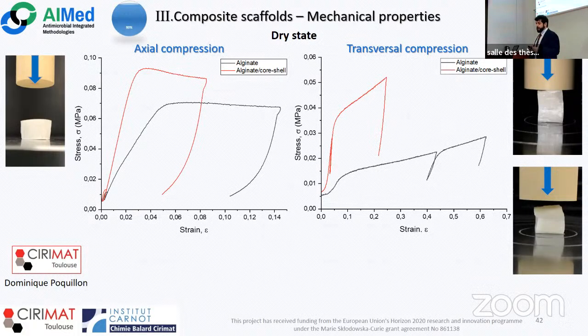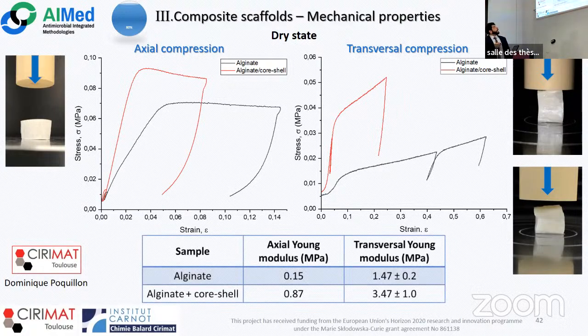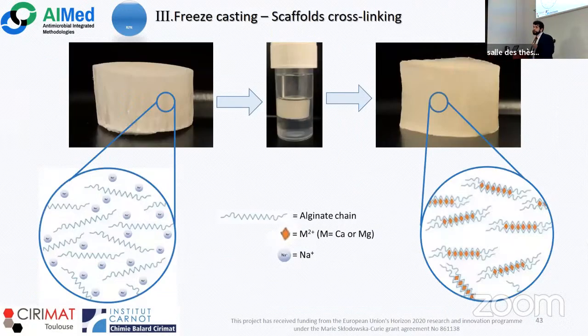Here at CIRIMAT, we also made some preliminary mechanical tests on the dry scaffold that we just prepared. And we can observe, comparing with the alginate scaffolds in black, both in the transversal compression and in the axial compression of a small square that we cut from our scaffolds, that we have a good increase of the mechanical properties in both directions by adding the core shell particles, because they impede a bit the sliding of the walls. But then we wanted to improve these properties, and we wanted to improve the stability of the alginate.